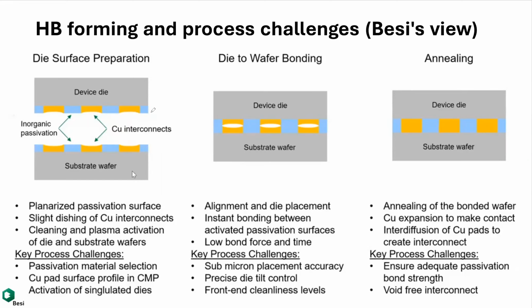Die to wafer, you need to cut it, right? When you cut it, all the chunks come out. It's not easy to deal with that, right? So, but let's focus on the simple process for now. So pretty much the surface of the hybrid bonding is that you have copper, and then this is oxide, usually SiO2. And you want to bond copper to copper and oxide to oxide. So this is a hybrid. And not just one bonding, but there are two bonding happen at this process.